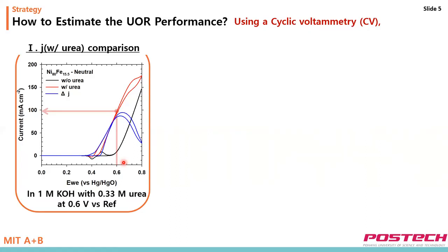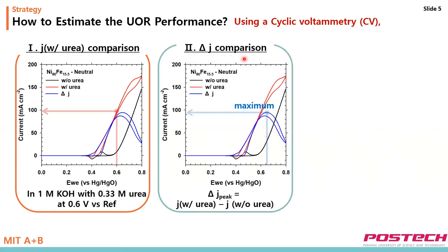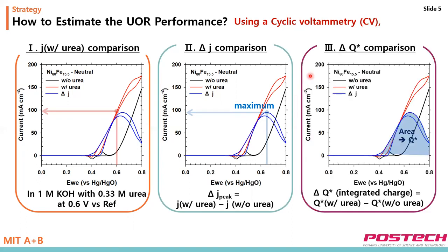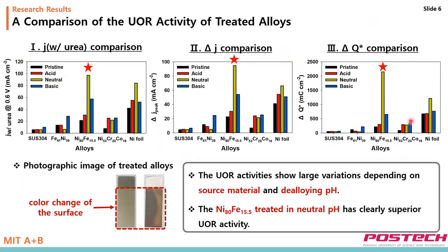In more detail, first, when urea is in the solution, compare the current value obtained at a specific voltage of 0.6 volt. Secondly, the peak current value can be obtained from the current difference depending on the urea. Finally, the amount of integrated charge of the current difference can be determined to estimate how much urea oxidation reaction occurred.